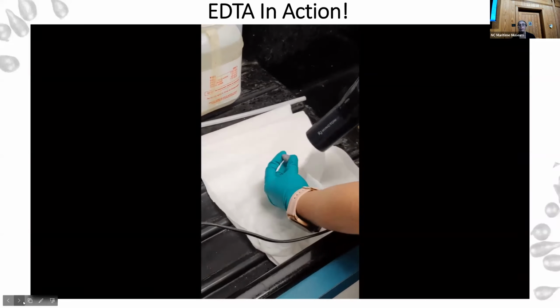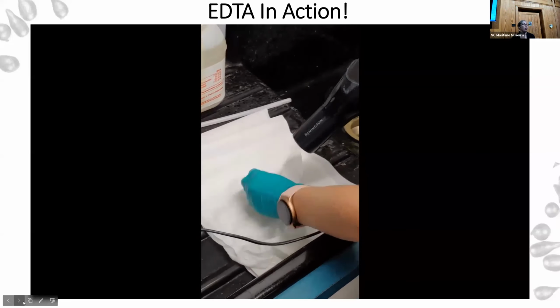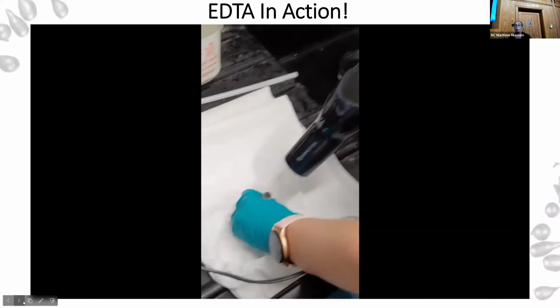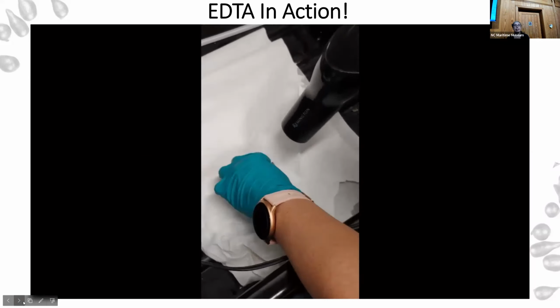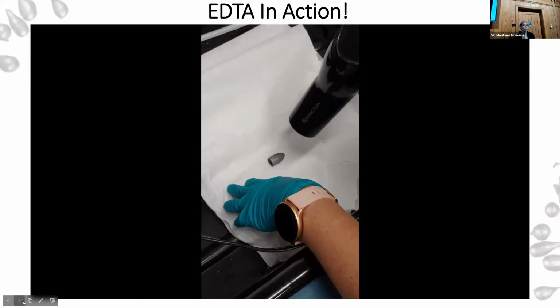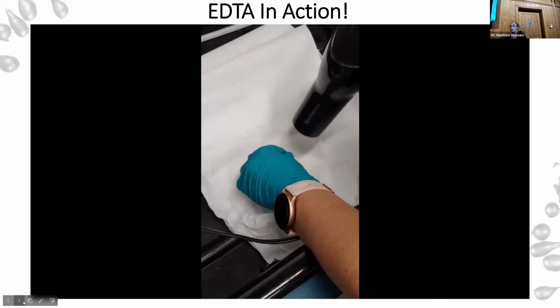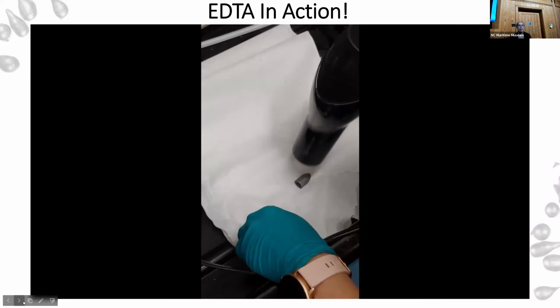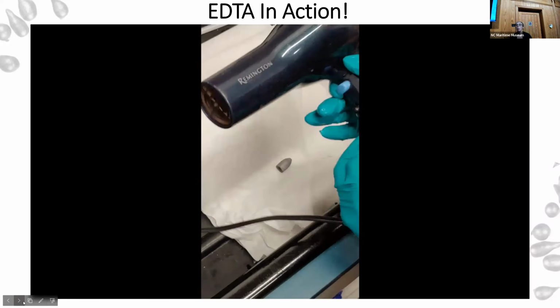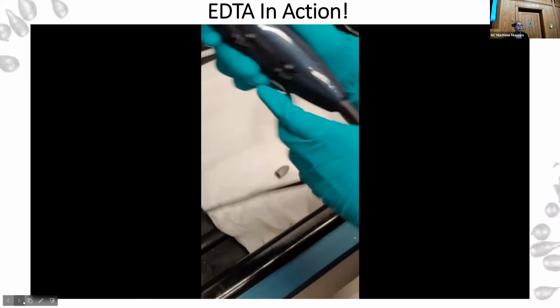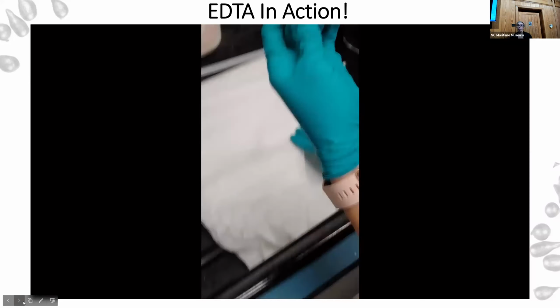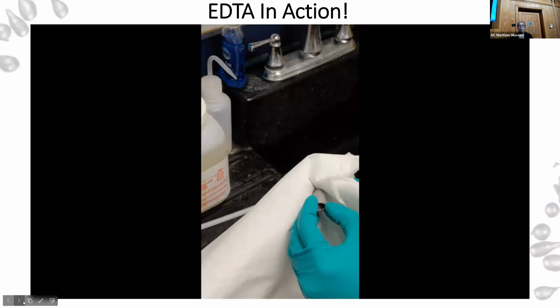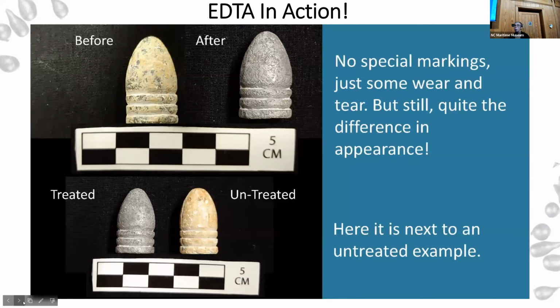It's also very important to dry your artifact thoroughly to remove any water deposits, especially microscopic water caught in the reservoirs on your surface, in any imperfections or pits. You can get very, very tiny pockets of water, which can then become pockets of chemistry. Those can basically cause corrosion. So you can do this slowly in a controlled manner, using something like a desiccation chamber where you very slowly and incrementally remove moisture and dry your artifact.